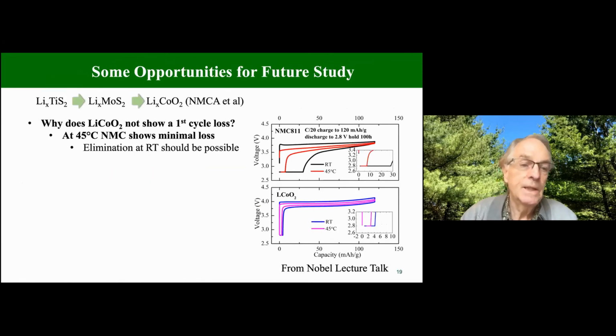The interesting question here is, why does lithium cobalt oxide not show a first cycle loss? And I show you some data here comparing 811 with lithium cobalt oxide. In black here is the room temperature data, 811, and you can see the large first cycle loss. Here's the data at 45 degrees centigrade, where it's almost all gone. If we then do a constant voltage discharge, we get it essentially all back. And this is just an enlargement of this part up here. Okay, so this has been held for 100 hours here.